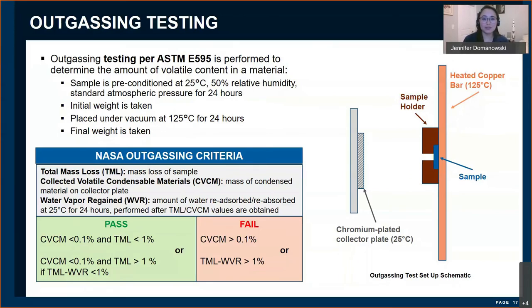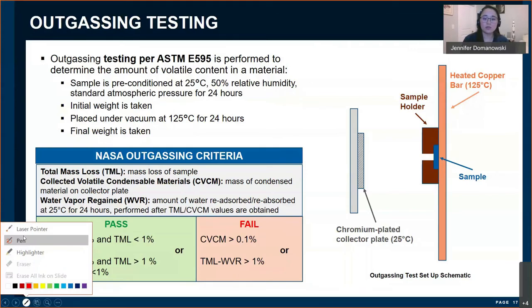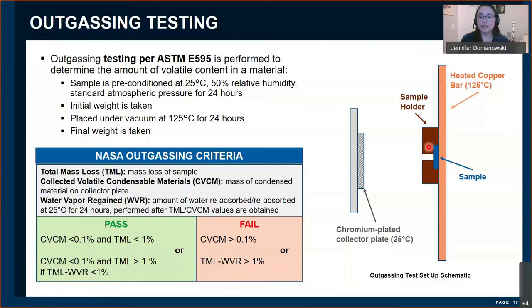And then here's how the test works. So what we do is we get the sample that we want to test, and we place it in this holder here, and it's completely enclosed except for this small exit port. And then it's attached to this copper bar. So we'll heat the copper bar up to 125 degrees C, and then the material will heat up, and any released species will travel through that exit port, and it'll condense onto this collector plate right here, which is kept at a cool 25 degrees C. So after that testing is done, we weigh the collector plate to see just how much deposited on there. And then if you wanted to see what species were there, you would send it to my labs to do that chemical analysis.